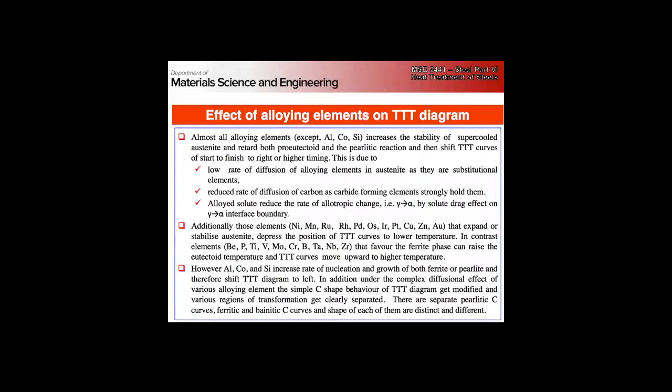I mean, austenite and ferrite stabilizers, because there we're talking about equilibrium phase, right? What is going to form? Here in the TTT diagram, we're talking about kinetics, right? So this is what phases can we reach in a finite amount of time, right? And that's different than if we hold it for an infinitely long time, what phases are going to show up.